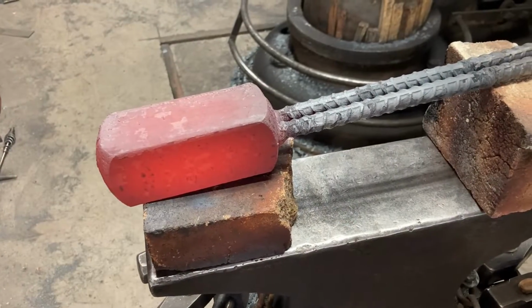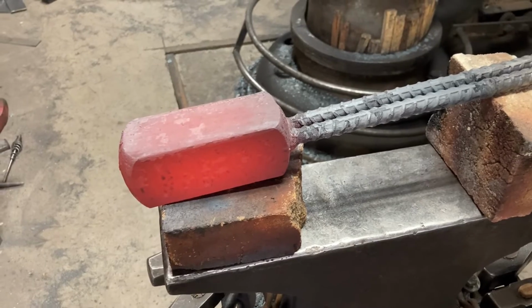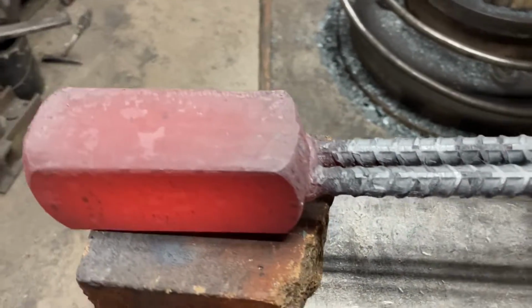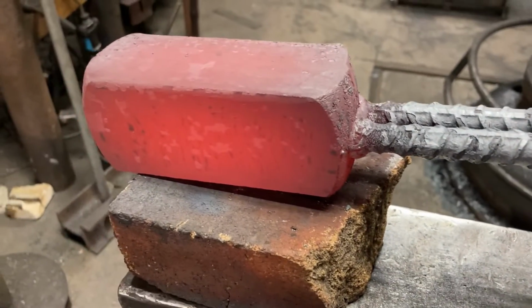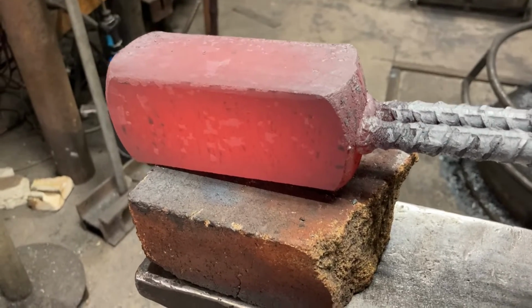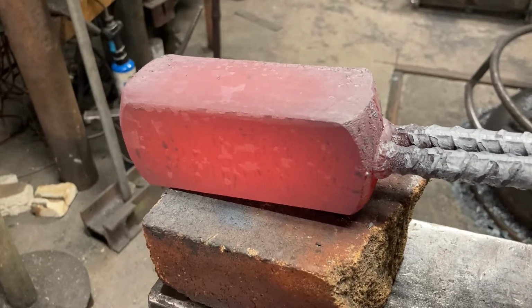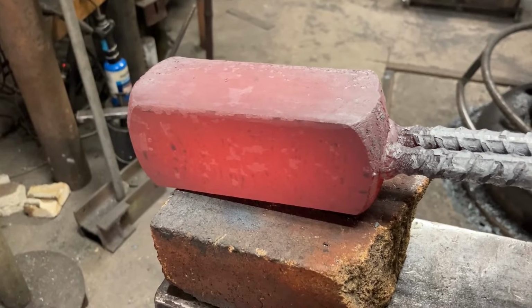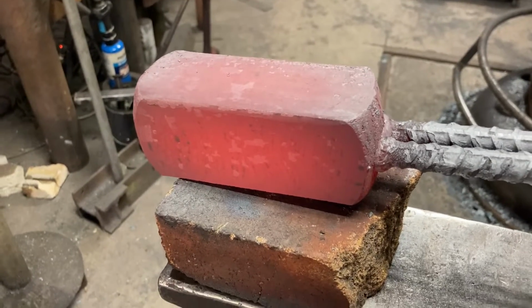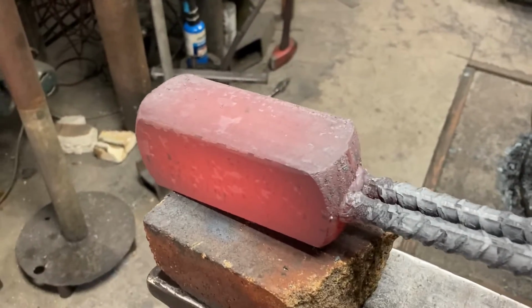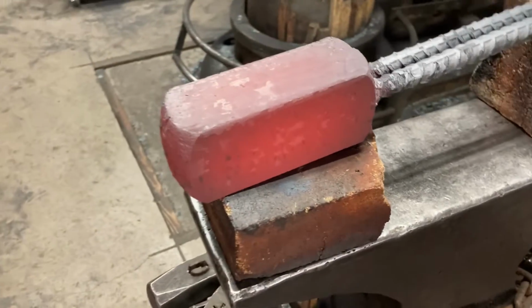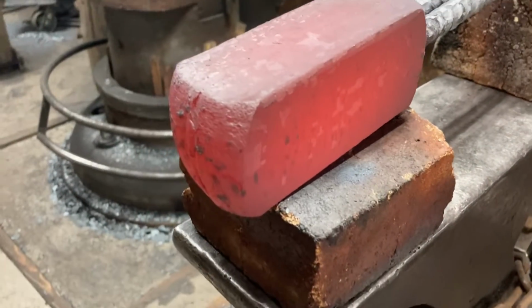And with that, the last forge weld on this entire billet is done. We have quite a good amount of material. Nothing like what we started with, of course, but not 50% loss, maybe 30-40% loss, which over the course of 5 days or so of working on this thing is not bad.